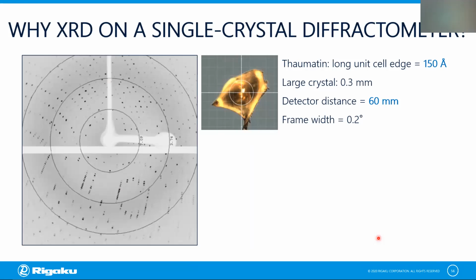The second example is a diffraction image obtained of a protein crystal, which is thaumatin. So thaumatin crystallizes in a unit cell that has one long dimension of 150 angstroms. So we brought the detector to a close distance of 60 millimeters, and that distance is really closely related to that long unit cell edge dimension. And we made things even worse by choosing a large crystal, which itself will enlarge the size of the reflections. And so with all that taken into account, we wanted to see how the reflections would still be resolved on the face of the detector.